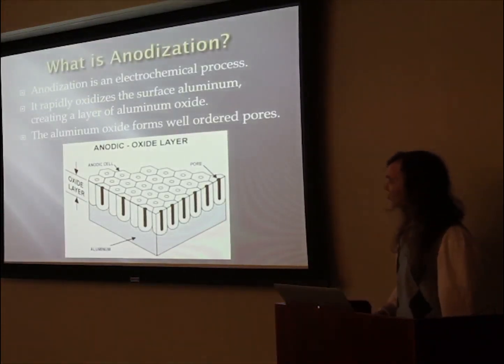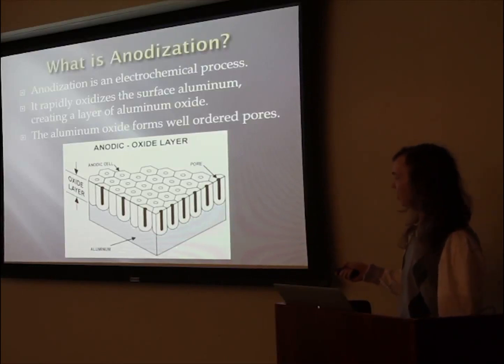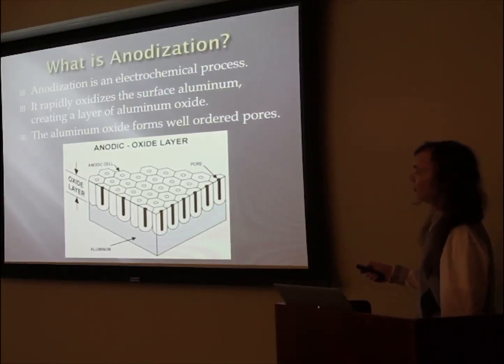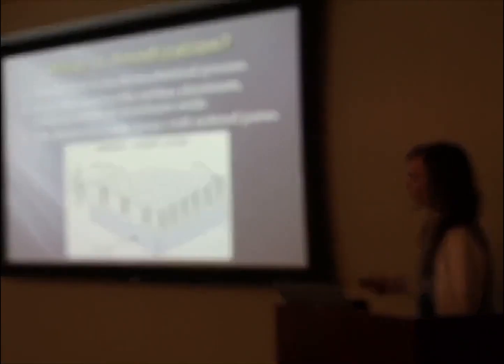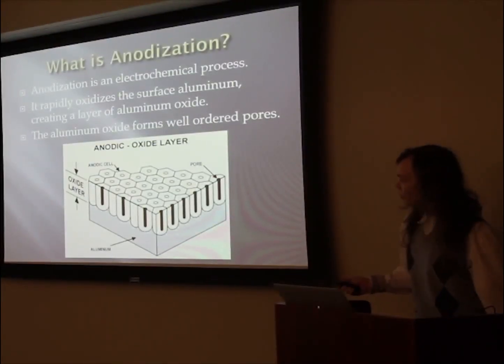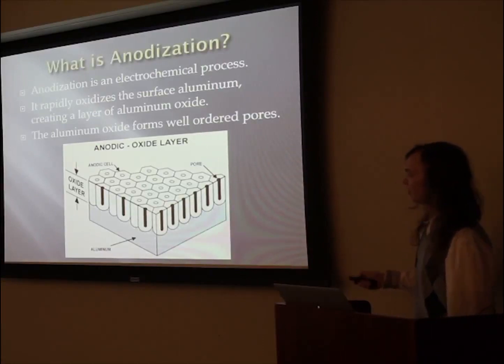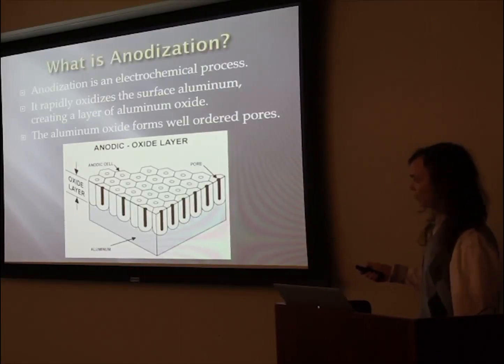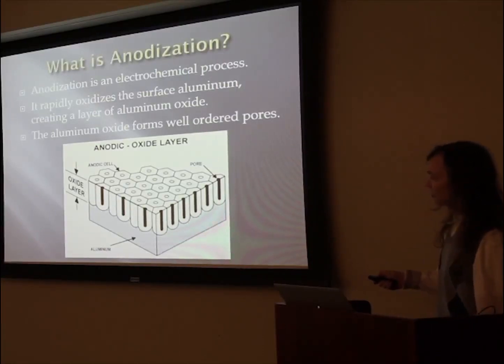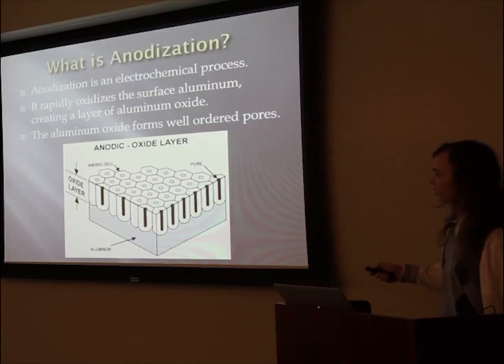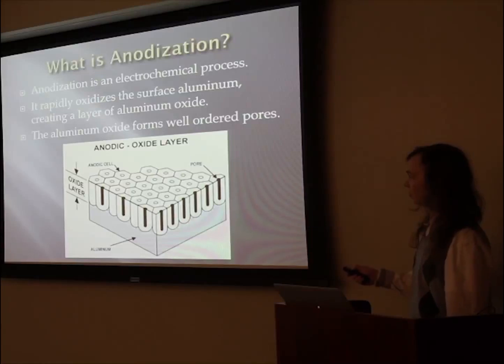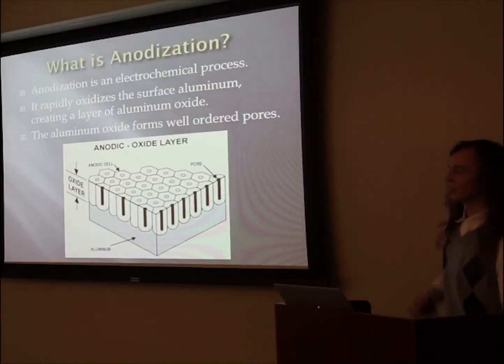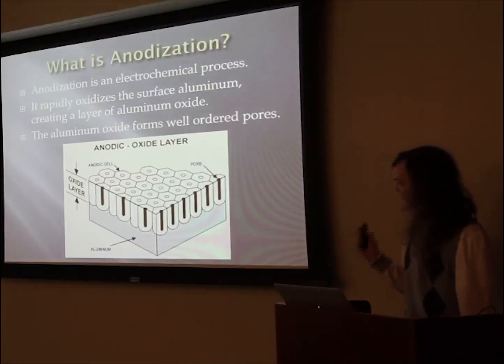So it's an electrochemical process where you are taking some aluminum sample and you're rapidly oxidizing it through putting some acid on the top and driving a current through it to increase the rate of oxidation. So what happens here is that you have a sample of aluminum, and by doing this anodization, you turn the aluminum substrate into aluminum oxide, creating this oxide layer here. And the cool thing about it is that you get these hexagonally ordered pores on the surface. That's the ideal situation you want to get out of it.